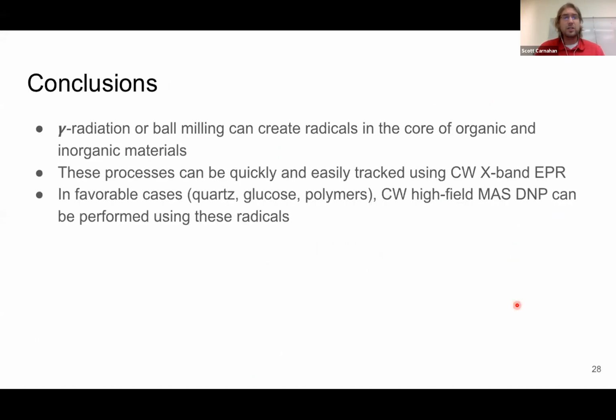So, in conclusion, what did we do? We showed gamma radiation and ball milling can create radicals in both organic and inorganic materials. We're able to track the radical concentration and the radical creation by EPR extremely easily. And in some of the better cases, we're able to perform DNP at MAS on these samples.